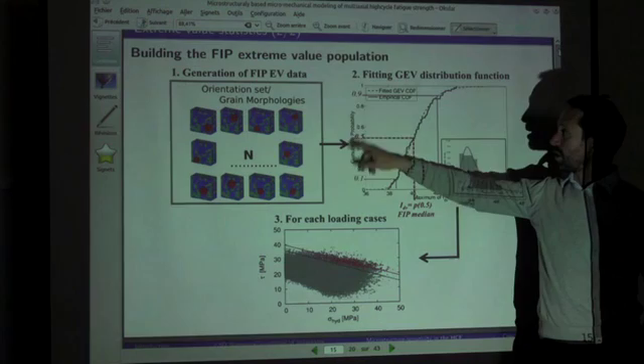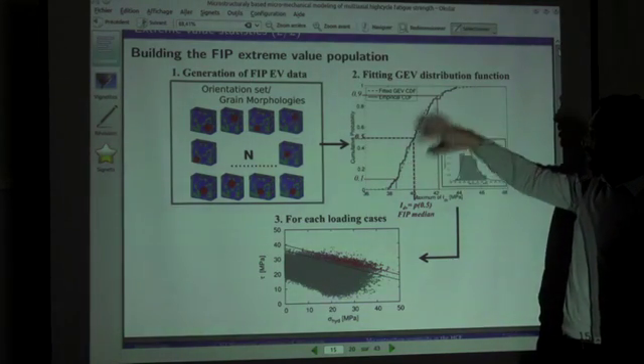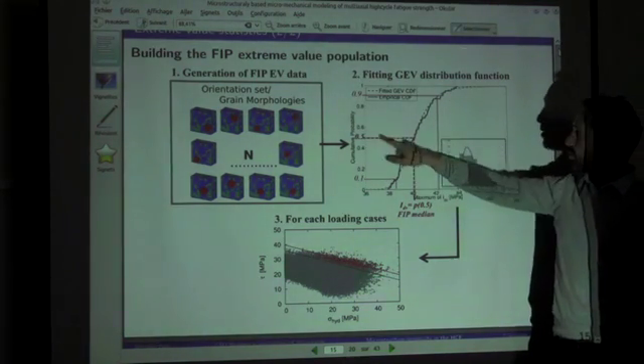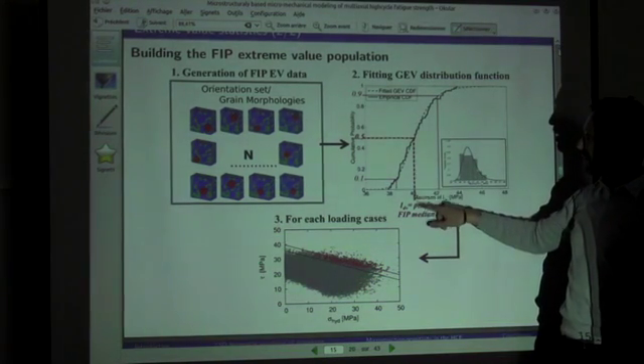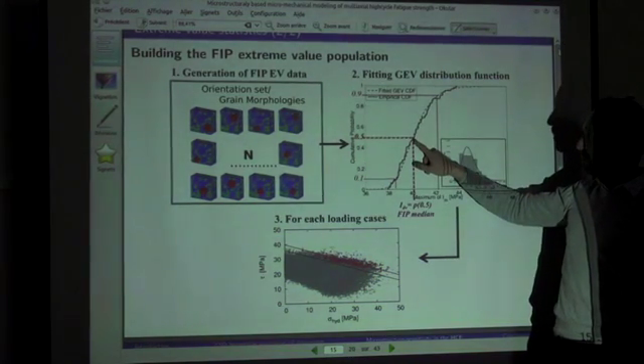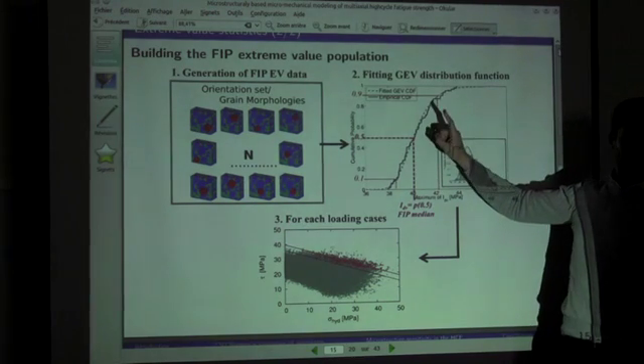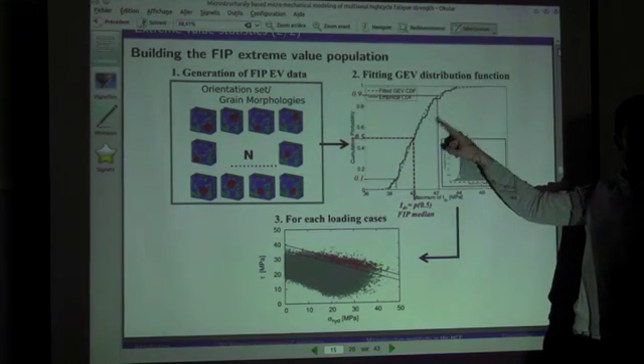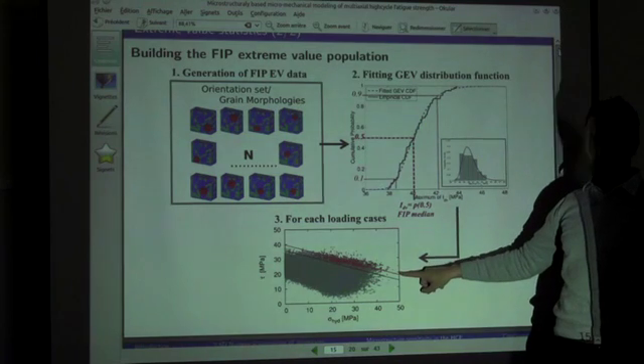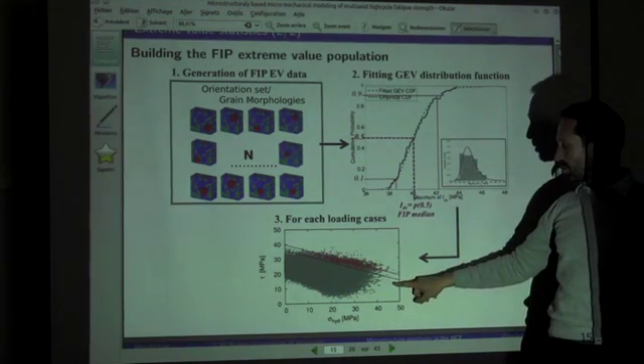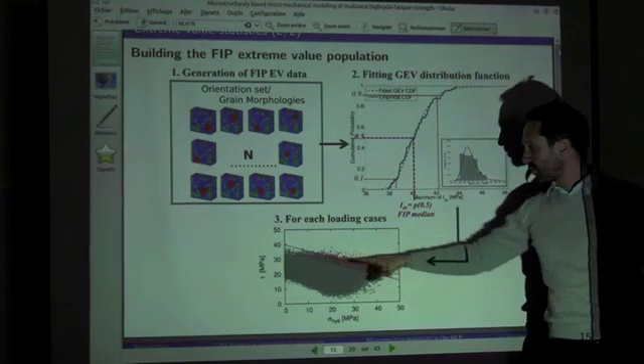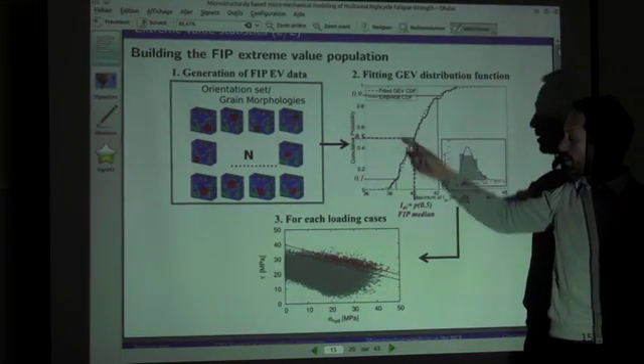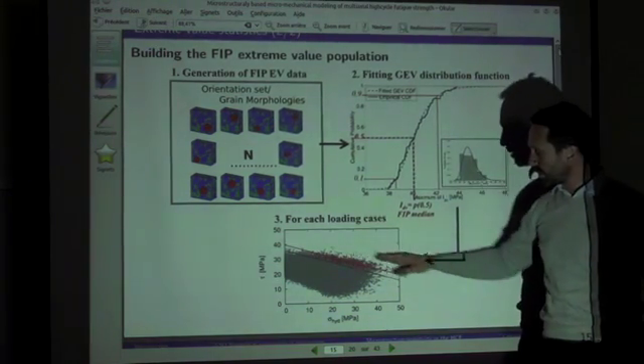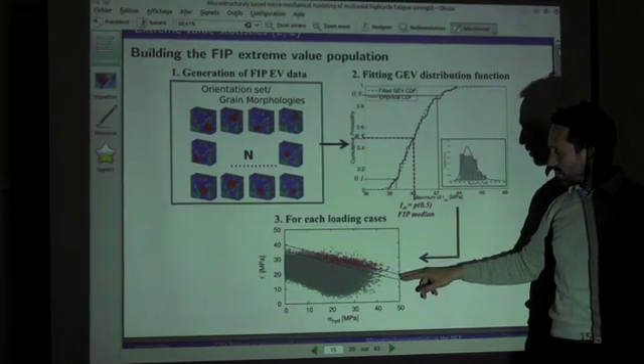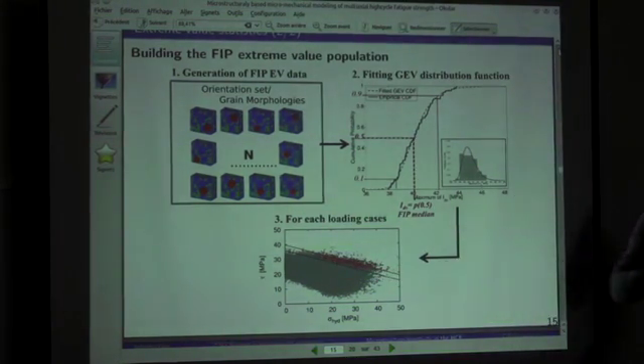And we are taking out of that data the extreme values, fitting our distribution, and obtaining a parameter that is an indicator associated to a probability of 0.5 of this particular distribution of extremes. And we are rebuilding a new threshold, which is not the macroscopic one, but the meso one, which fits more or less with this probability, but you can change the probability if you want to have a higher threshold, that fits the extreme value computation and gives an indication of the extreme value response.